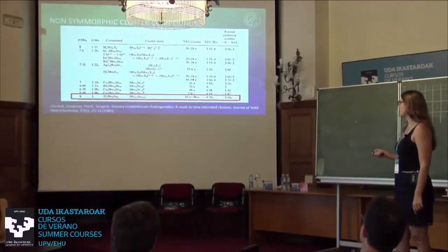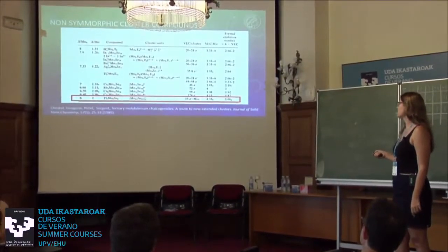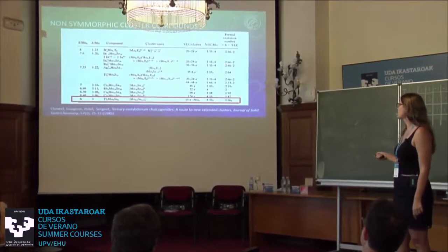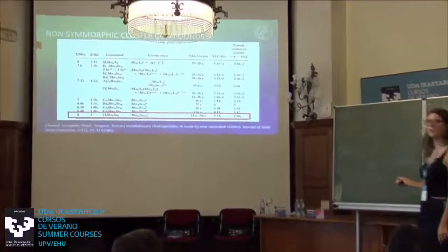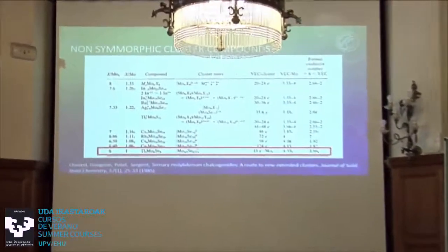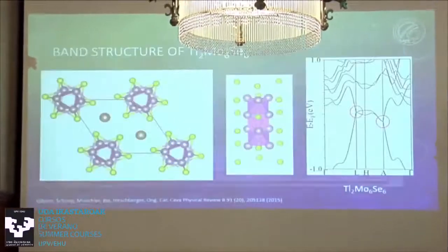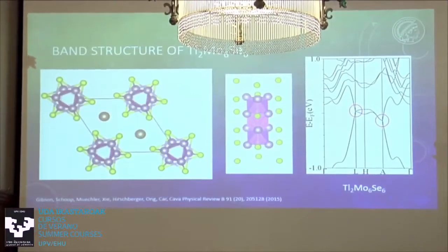And if you look at the compound where this infinite cluster was there, it was actually not a charge balanced compound. So it has 4.3 valence electrons per molybdenum, something odd. So then, with Quinn also at Princeton, we looked at this compound. And so here again, you can see the screw. You have 3 molybdenums in this direction and in the other one.